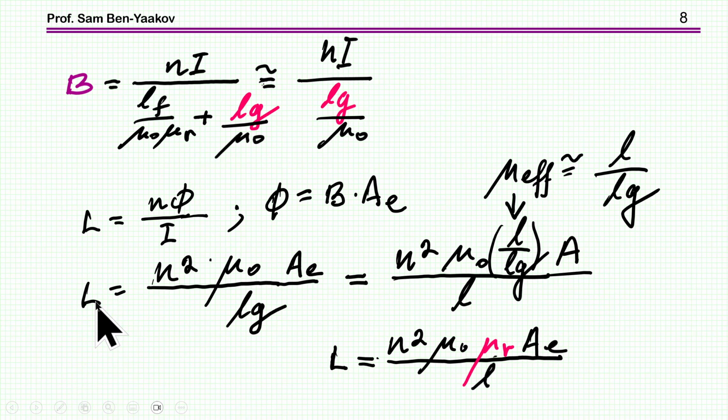But I can show it in a nicer way by reworking this equation to this form. What I did here, I've divided it by the magnetic path length, the total or the ferrite, which are about the same because the gap is small. So rather than just having L sub g, I've replaced it by the magnetic path length of the total core, and then divided it by the gap.